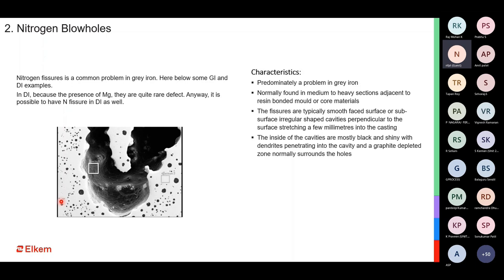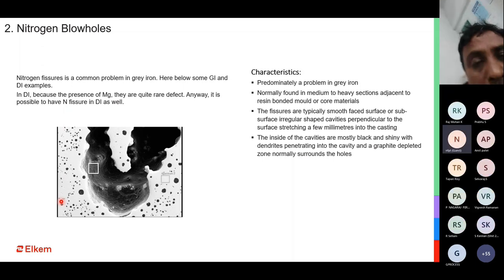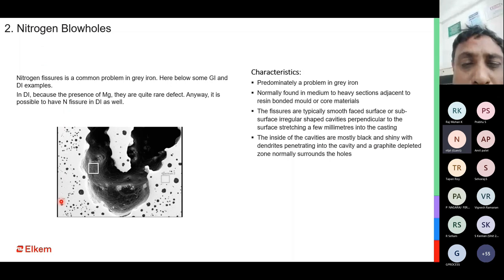Why is it caused first? It is caused mostly in heavy section castings, close to the core or close to the resin bonded mold. It has a much smoother appearance compared to gray iron nitrogen fissures. Gray iron fissures are much more sharp and irregular in shape, but it's much smoother in ductile iron. It has the same black, shiny, dendritic appearance inside, but the dendrites will not be as pronounced as in gray iron castings.